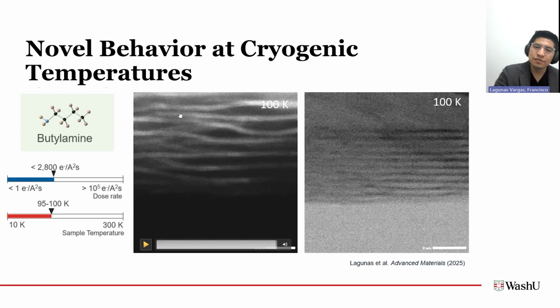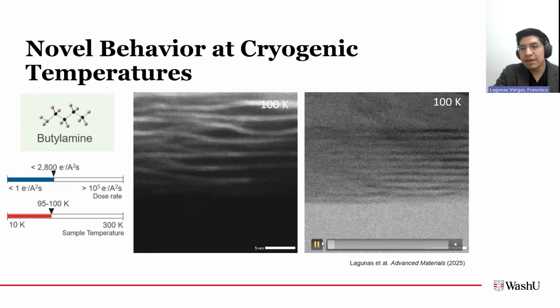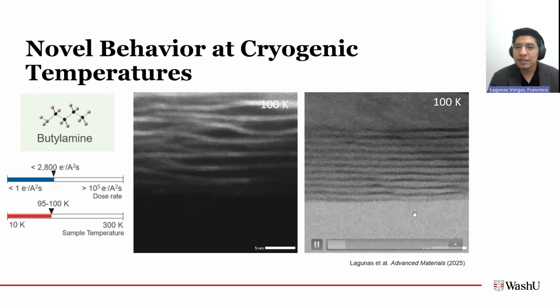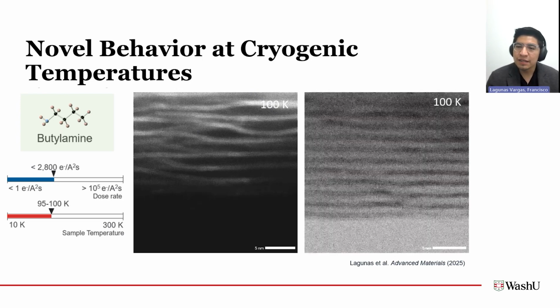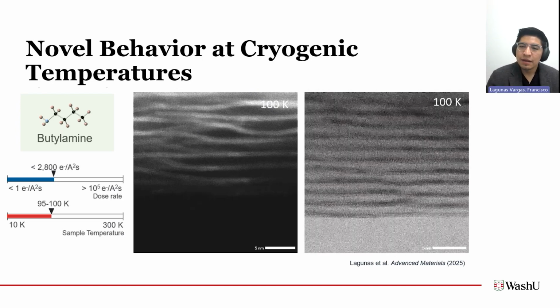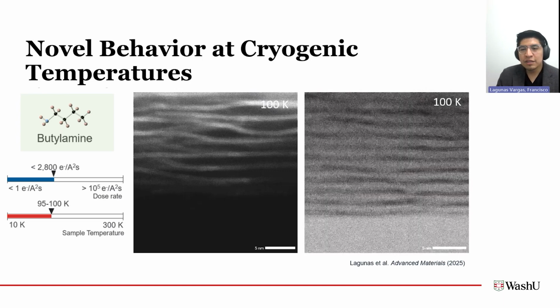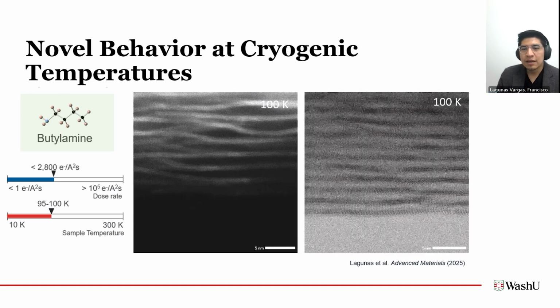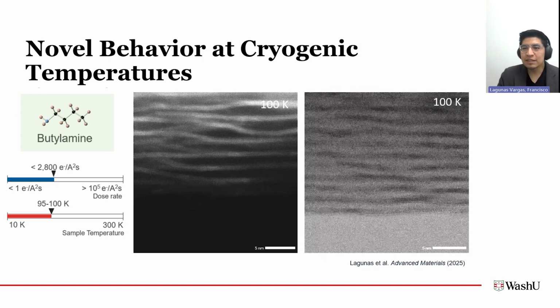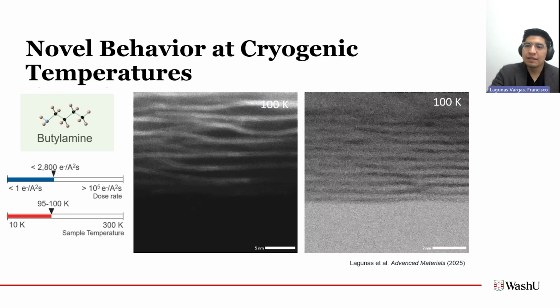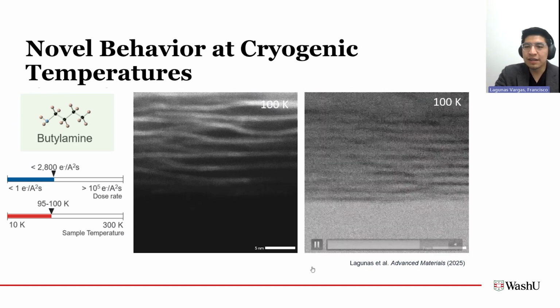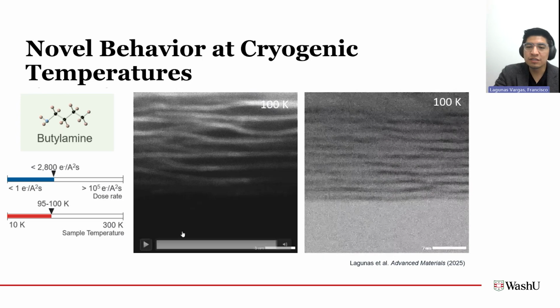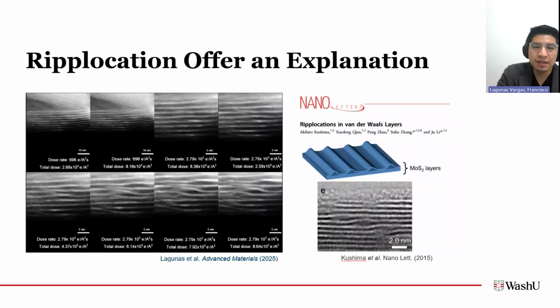So you can see the formation of all these different little Y defects, where it would go from one layer to two layers. It looks like a little Y fork. And then this effect is actually quite reproducible. So here's another region in the sample that we did it. And you can see we're increasing the accumulated dose in the sample. You can see there's a little bit of wiggling that's happening. And then if we zoom out, we can see we've clearly affected the structure of this material in a pretty significant way.